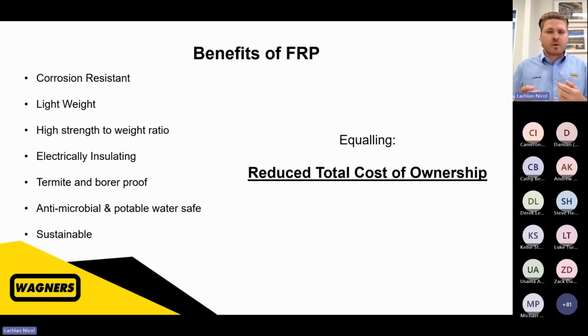It's part of that different design approach: we would typically design around our service limits, so deflection limits for a bridge or a boardwalk, compared to the ultimate strength where you would normally design for steel. It's also electrically insulating. I'll talk a bit about electrical infrastructure later on, but that's a key thing for safety in the electrical infrastructure business. If an insulator on top of a power pole failed and the line held up against the utility pole, you wouldn't get touch potential down on the ground, so it is safe. It's insulating from electrical conductivity, which is a great benefit for light poles, cross arms or power poles.